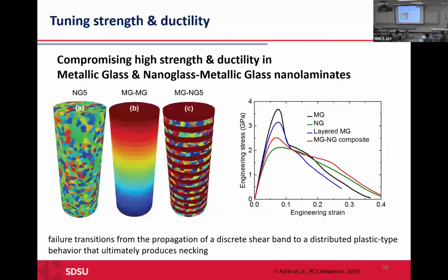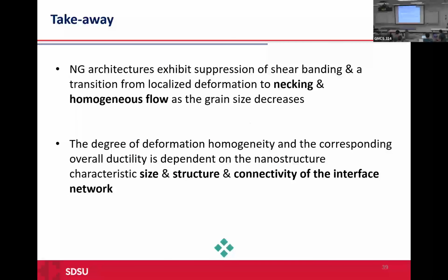Going from metallic glass and changing the microstructure of the material to nanoglass, we could see a transition from very localized plastic deformation to some plasticity and some type of necking. The takeaway from this point is that by changing the microstructure and implementing some type of interface in the microstructure of the material, we could separate the dominant shear band formation, and we could transition to some type of homogeneous flow as the grain sizes get smaller.